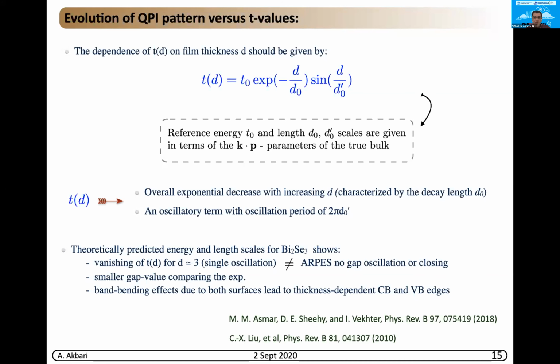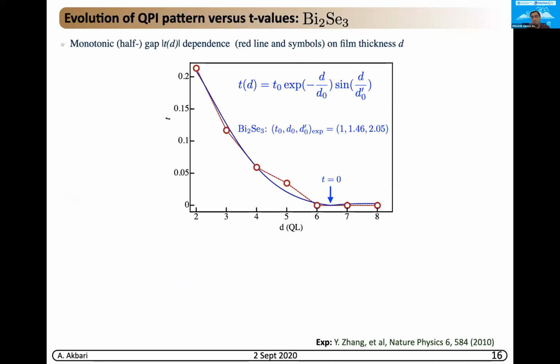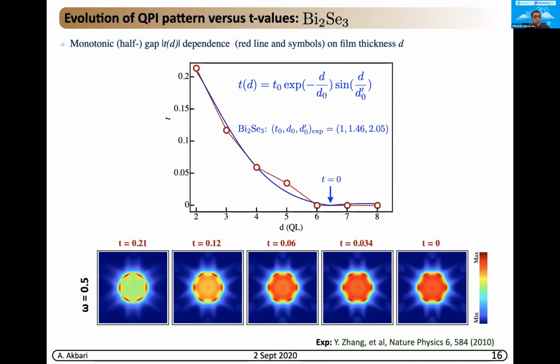So for this reason, I took the first result from bismuth selenide, the hopping parameters from the ARPES data, and I ran the calculation for QPI, and you see that we see certain changes. Mainly, for the higher hopping, we start from the drop-like feature, and this drop-like feature, with increasing hopping, that is, with decreasing thickness, shows a smooth decrease. Therefore, the QPI feature also smoothly changes to the snowflake feature.